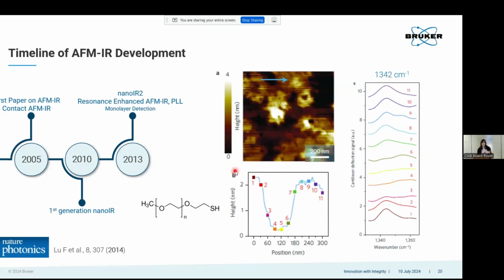And so in 2013, other researchers started looking at this, and they figured out ways that if you resonantly excite the cantilever, instead of just using a single pulse at a time and measuring it out, if you actually use the cantilever as an amplifier, you're able to measure much, much thinner materials.